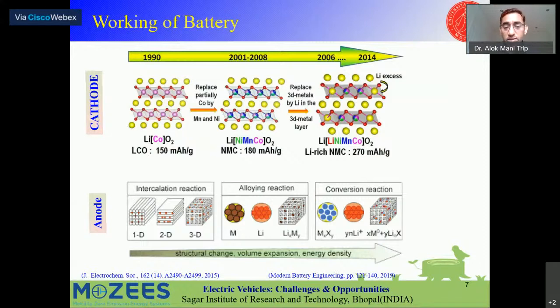So one is the alloying reaction, where lithium forms alloys with the metal used and expands. Then we have a conversion reaction, where lithium doesn't alloy with the metal, but reacts with the counterpart of that and then converts back. So in anode, we have three technologies. In cathode, we have multiple, but here I explain two technologies, layered and spinel based material. And both have a plus and minus. All materials have a plus and minus.